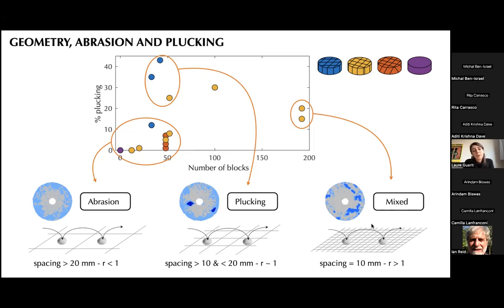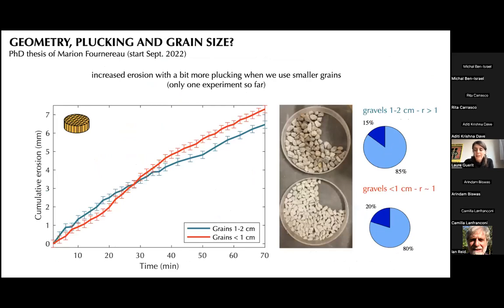So this is where we are today. We think that the ratio between the spacing of the fractures or the size of the block and the size of the sediment strongly influences the mode of erosion, whether it's abrasion or plucking that dominates, and thus the intensity of erosion. So to support this idea, we performed one additional experiment with a dense network, but we used smaller grains so that this ratio is different, and it is close to 1.